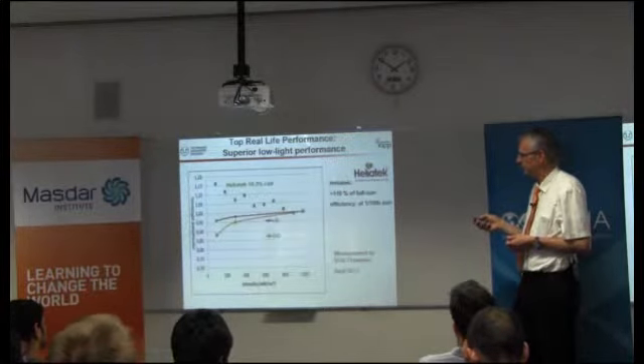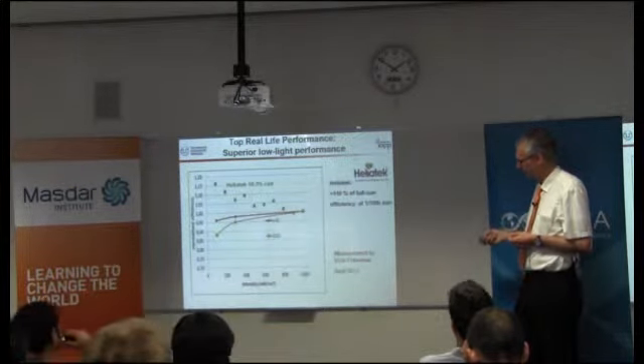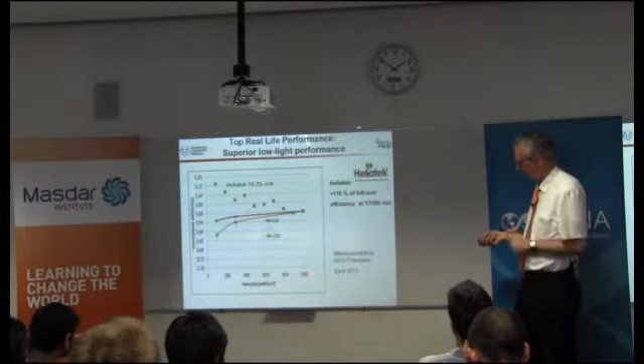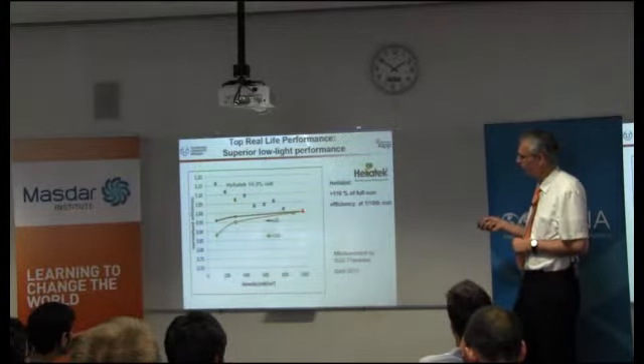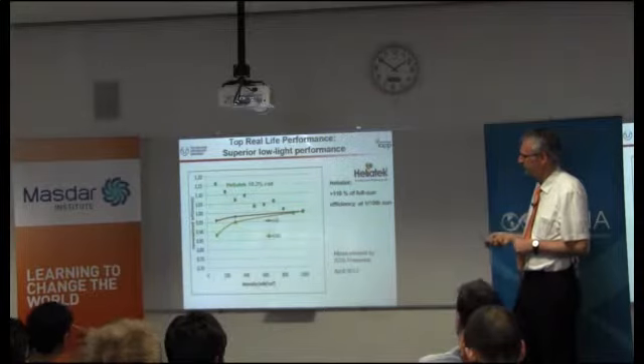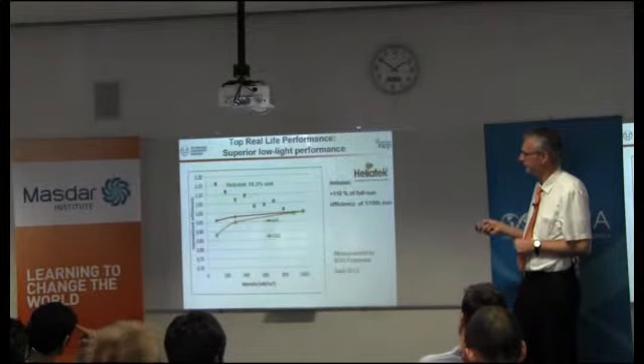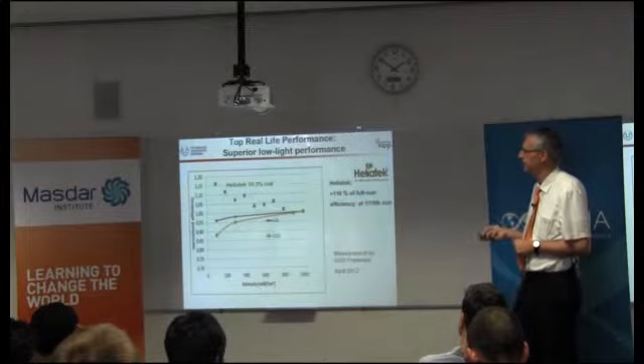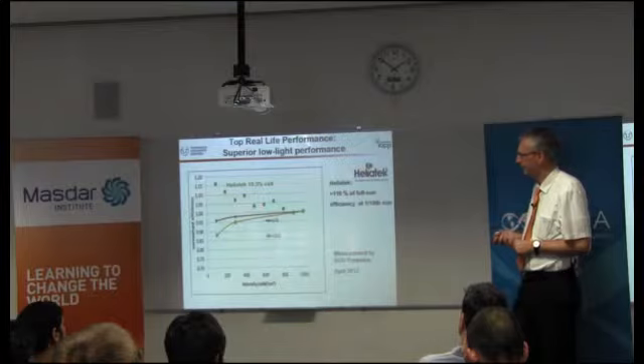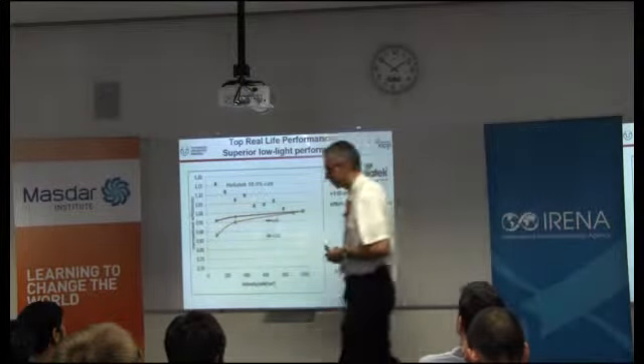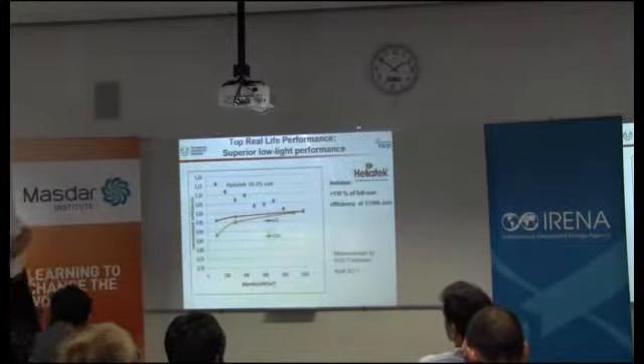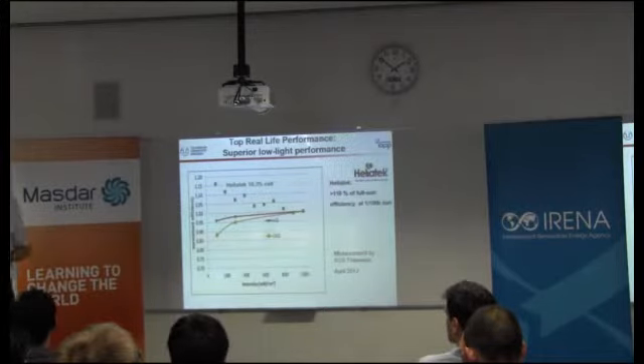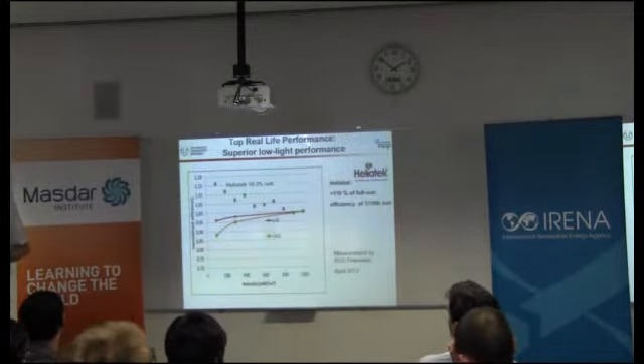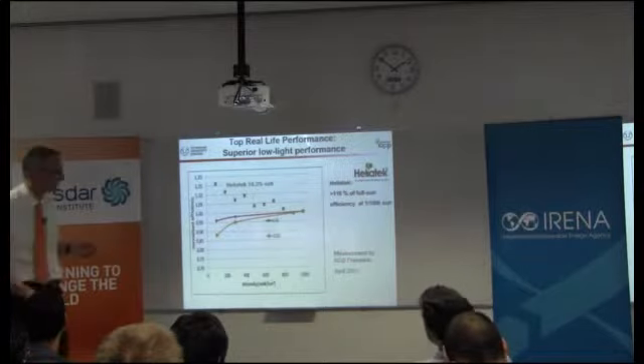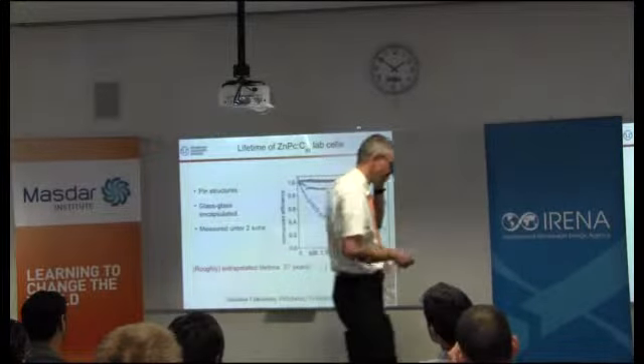And if you take the intensity effect, it's the same way. When you go down from one sun, organic goes up significantly. In many cases, it has a maximum at about 0.1 suns. It can be about 10 to 15%, whereas crystalline silicon and CIGS actually get worse for lower intensities. So again, in the morning and the evening, your organics does better. And finally, there's a small angular effect.